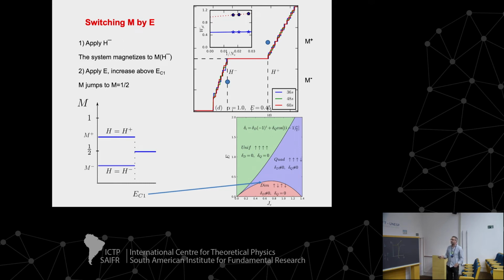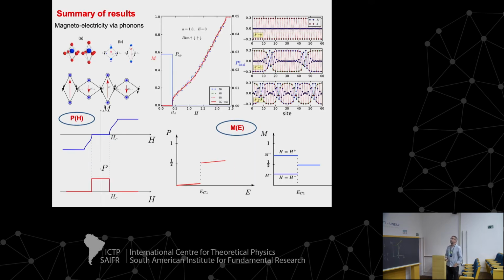But essentially, you can also change with an electric field. You can change the pattern of the deformations. This is the main message. So with the electric field, since they are coupled, the dipoles are coupled to the deformations. So with an electric field, you can change the deformations from a dimerized pattern like this to something else, and then homogeneous. And then you could modify the magnetization with an electric field too. This is less interesting because, as I said, first you have to put a magnetic field to go up there, and then it's not so cheap anymore. So we are still working on that.